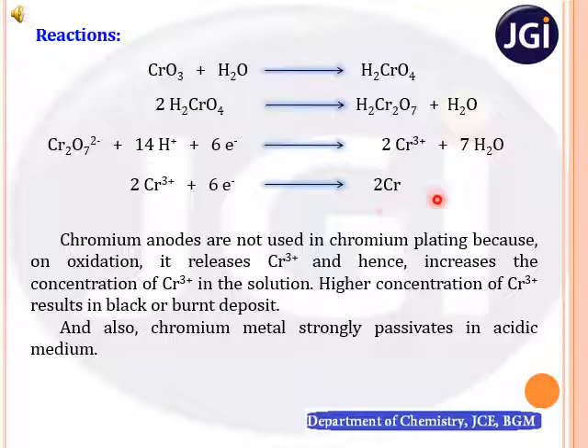This is about electroplating of chromium. Here one point to be discussed is that we are not using chromium metal as the anode. Instead we are taking chromium metal ions in the electroplating bath. The reason is, if we use chromium as the anode, it undergoes oxidation. On oxidation, it releases Cr3+, and hence increases the concentration of Cr3+ in the solution. As I said, if the concentration of trivalent metal ion increases in the solution, we will not get uniform deposition. Instead we will get a black or burnt deposit. This is one of the reasons why we are not using chromium as the anode.